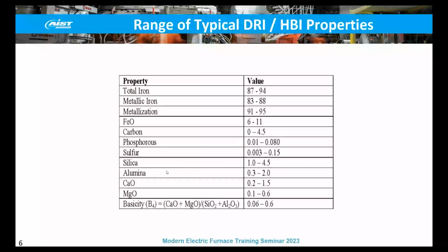So looking at kind of what the makeup of DRI HBI is: total iron content, 87 to 94%, but generally that's not all metallic iron. So we're talking about metallization and metallic iron—metallic iron probably 83 to 88%. And this will vary wherever you go, and maybe how close you are to where the DRI was produced, the time frame, how long it sat around, things like that.